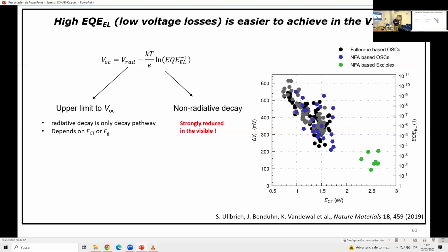We thought, because everybody makes solar cells with the gap around 800 nanometer, because that's good sunlight. If you consider the solar spectrum and you use a band gap of 800 nanometer, you absorb a considerable part of the solar spectrum, but you still keep enough energy to have a voltage. Going to longer wavelengths, gaps would lower the voltage, and it's always this trade-off. So most newly made organic solar cell materials are around 1.5, 1.4 eV here. That's why there are so many data points here.